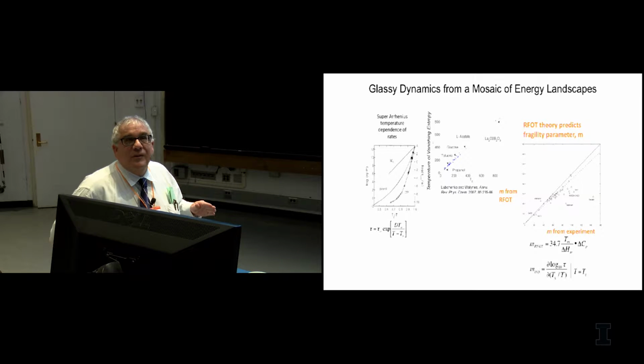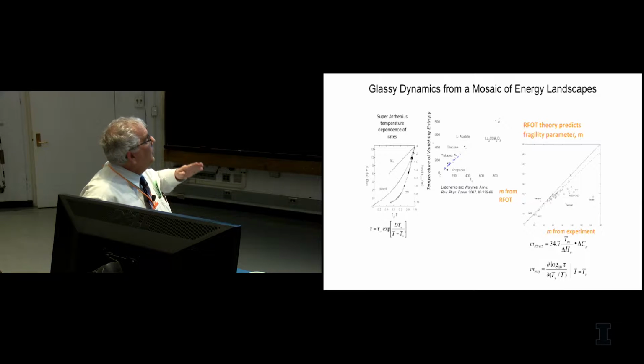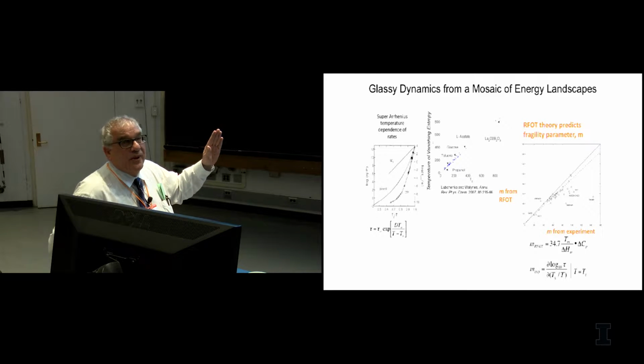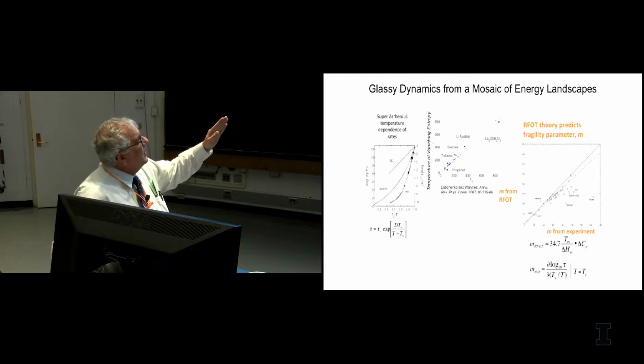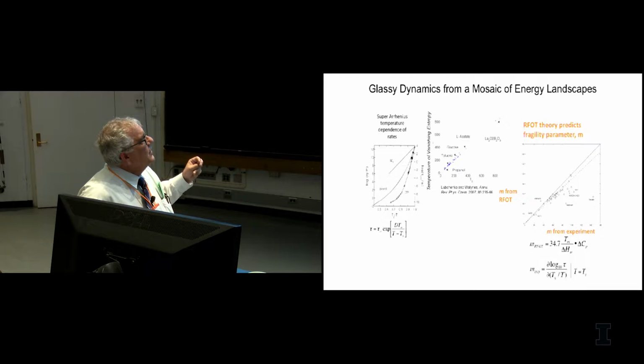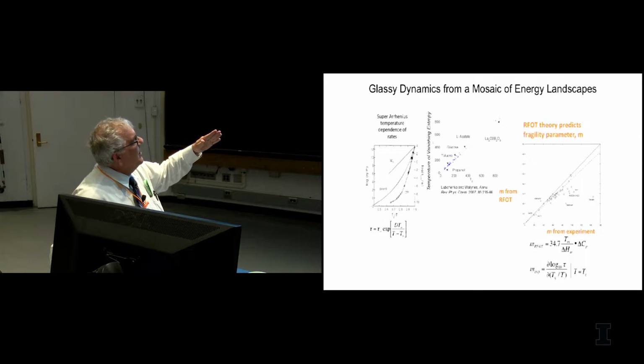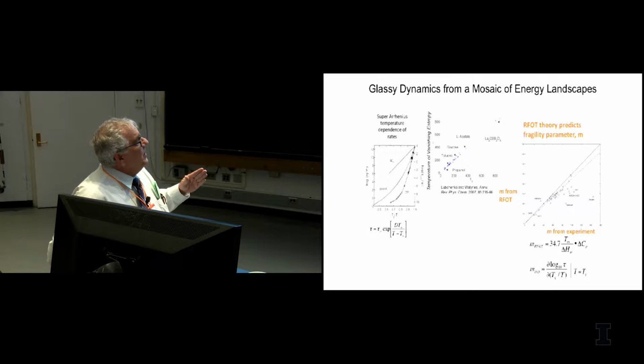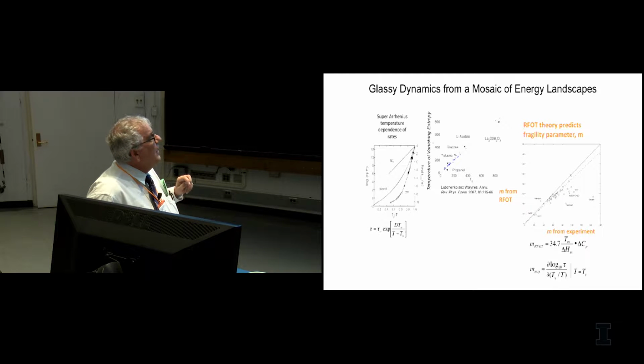Well, the theory has another consequence, the one that I just described. If you say, what is the slope of the curve at the relaxation time that corresponds to an hour, that activation enthalpy is called the M value when it's written to the base 10. The glass people are technical people. They use base 10, not base e. And the theory actually predicts that that depends on the temperature. It depends primarily on the heat capacity change when you get trapped. That's measured. So the theory actually predicts the Arrhenius slope at the point where the relaxation time is, let's say, an hour. That's called the M value.